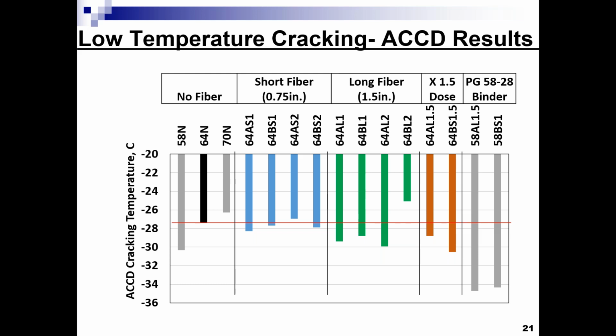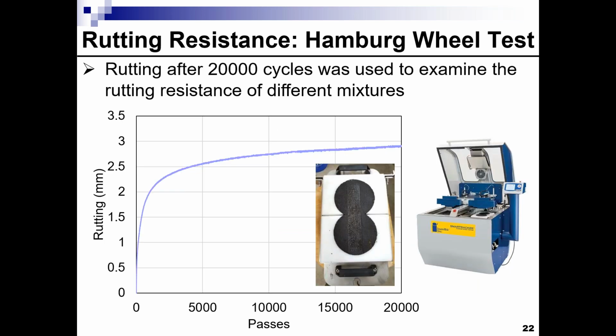Basically seeing that it did not adversely affect the low temperature cracking, but at the same time, it did not really improve it. This is something that was actually consistent with previous studies that have been conducted on Aramid fiber.